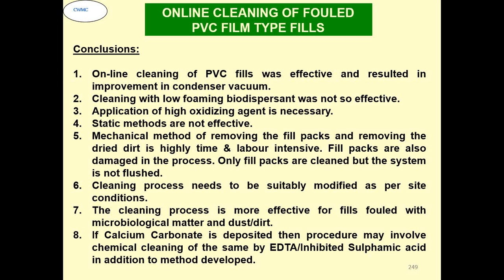So in this case, what we concluded is that normal biodispersants which have anti-foaming agent are not so successful, but the surfactant that we use along with the dispersant worked very well, and we were able to clean the systems pretty well. We need a certain amount of foam, but we have to be careful that we are not generating too much foam.